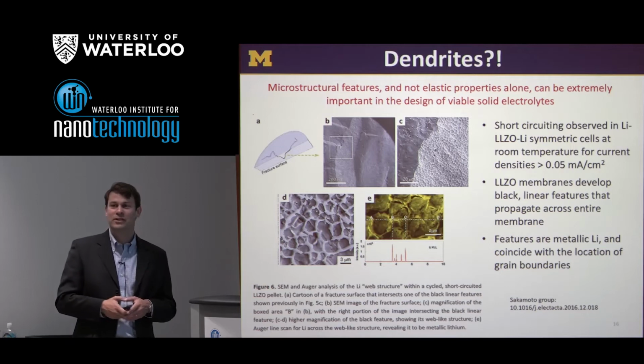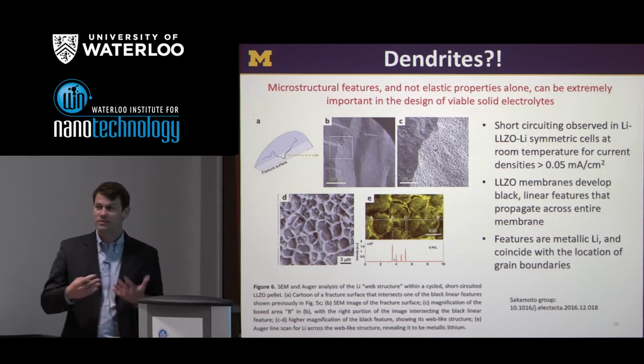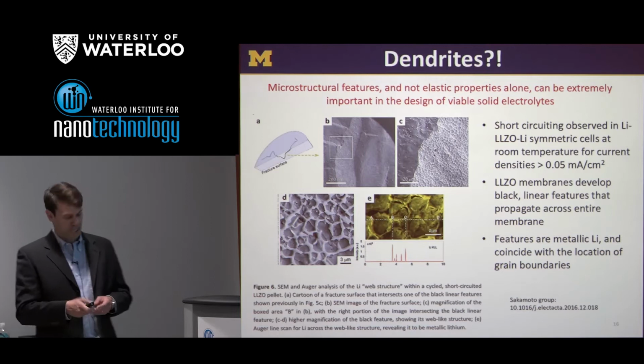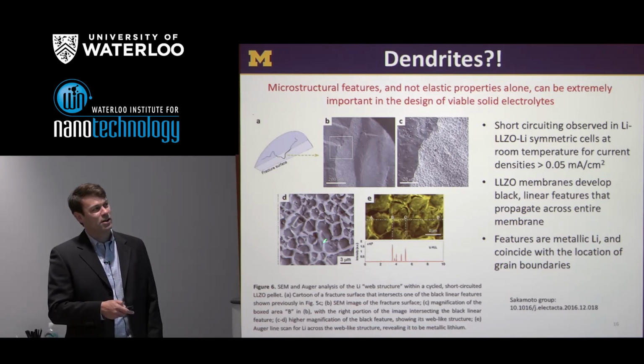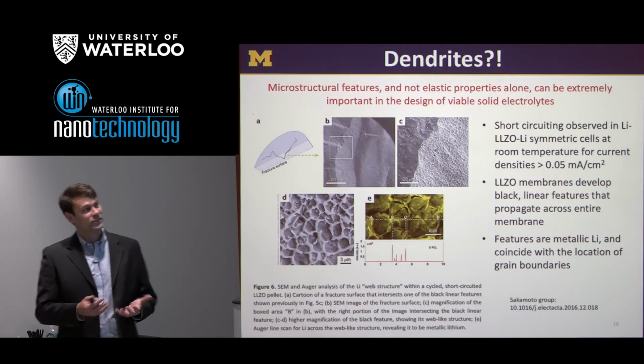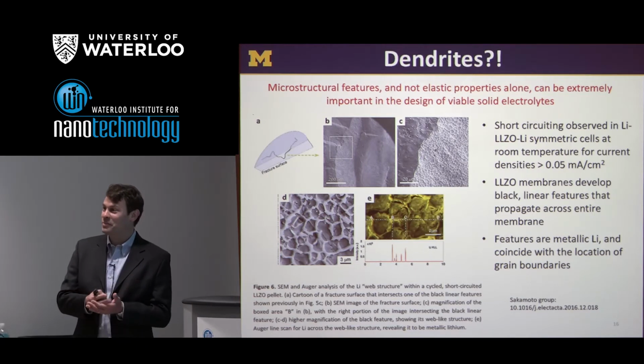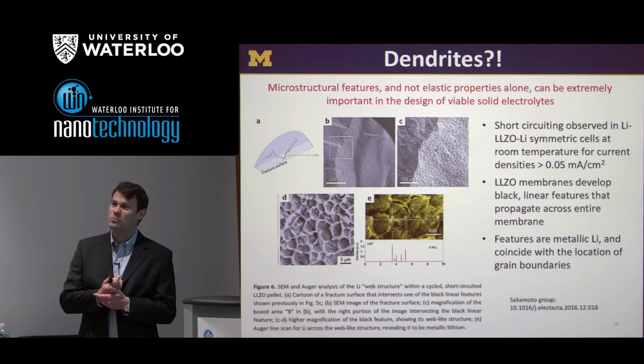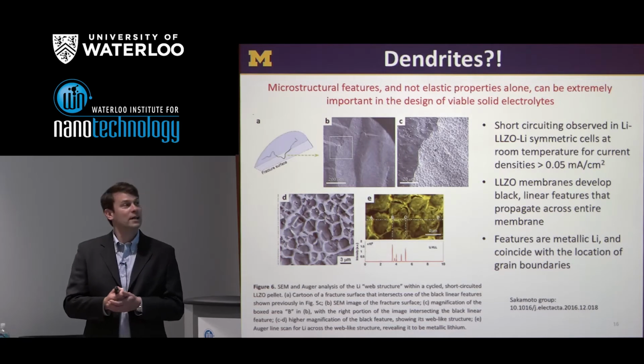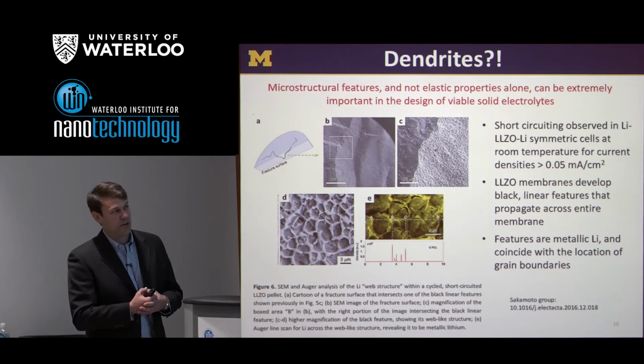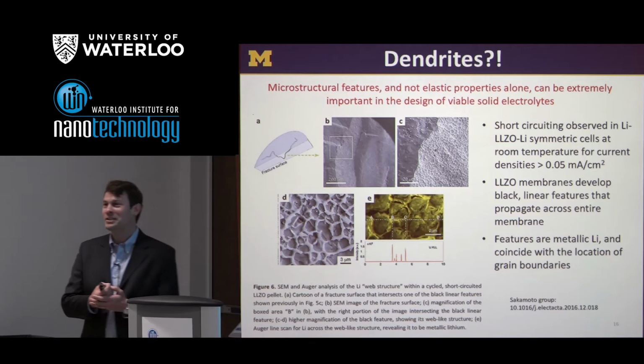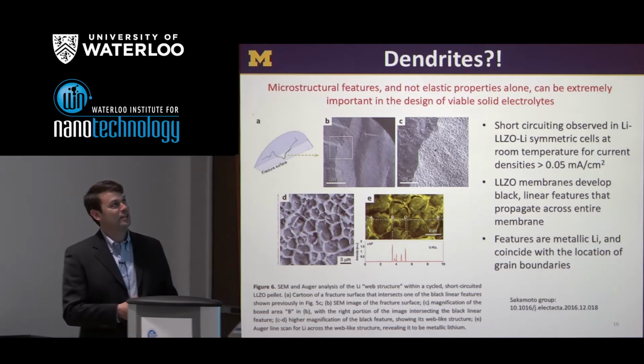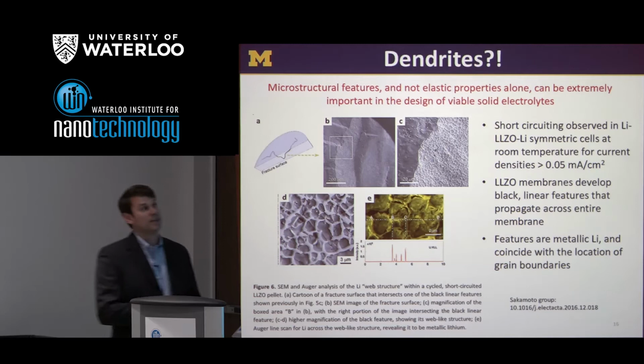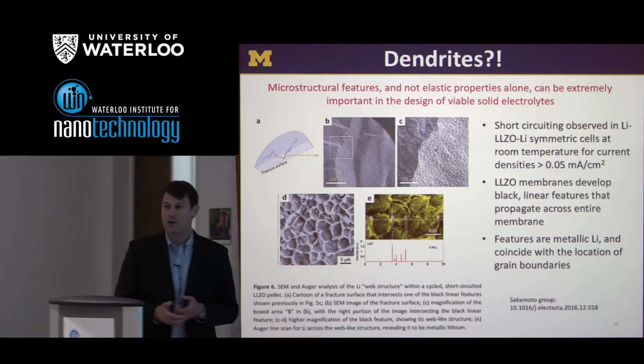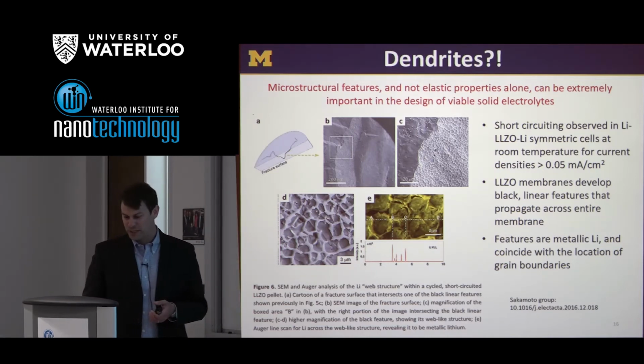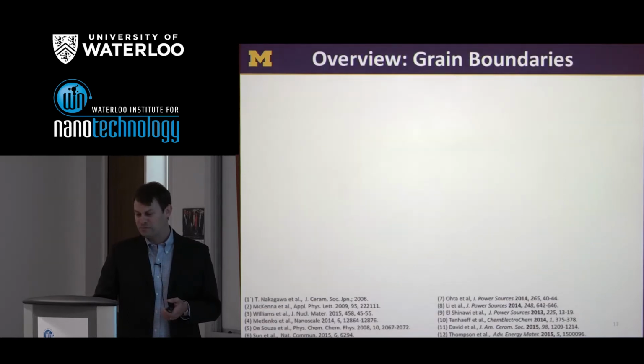And dendrites, I think, here should be used in quotation marks, because these are of course not dendritic microstructures. But we are seeing lithium metal penetrate along the grain boundary network. Based on a strict interpretation of the Monroe-Newman model, we would not expect this to occur. But of course, the Monroe-Newman model knows nothing about microstructure, so we shouldn't be too harsh. The message here is that microstructural properties are also probably very important in solid electrolytes that are polycrystalline materials, but so far haven't received much attention.